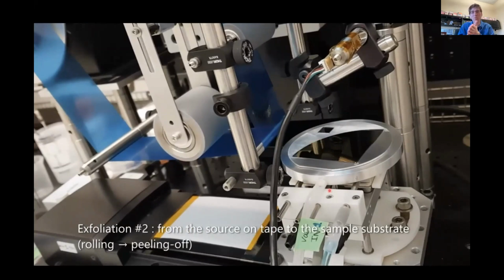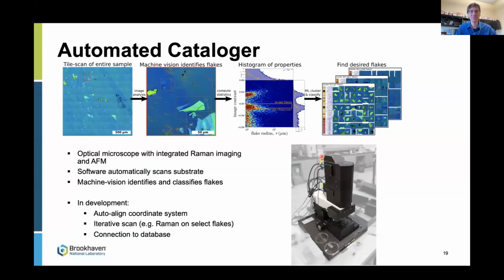And the reason we're doing it with a robot is it can be much more reproducible than if a human did it, right? So we can measure exactly what pressure we used, and we can use the same pressure every time. We can control the pull-off angle of the tape. We can control the temperature of the substrate, and it turns out that's quite important. So by controlling all of these parameters, we can tune and optimize it for a new material to get really good quality transfer, which means really nice flakes. And we're trying to get as many big, unbroken flakes that are thin as possible, right? So it's still a statistical process, but we're trying to make it more efficient than the manual method.